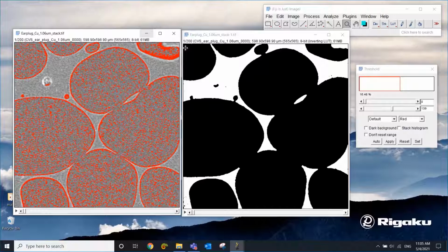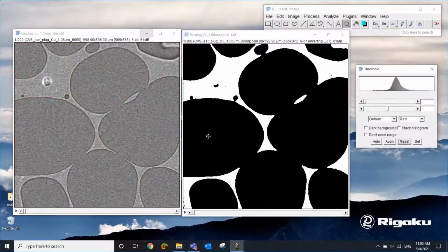But when you do smoothing, for example, always remember that you are manipulating the original image, and that manipulation can cause artifacts. In this example, you can see that there is a clear polymer wall here between two pores, but after the smoothing, that wall is gone. And this type of change of the image or the results can always happen when you do smoothing. So when you do this type of processing, do this cautiously.